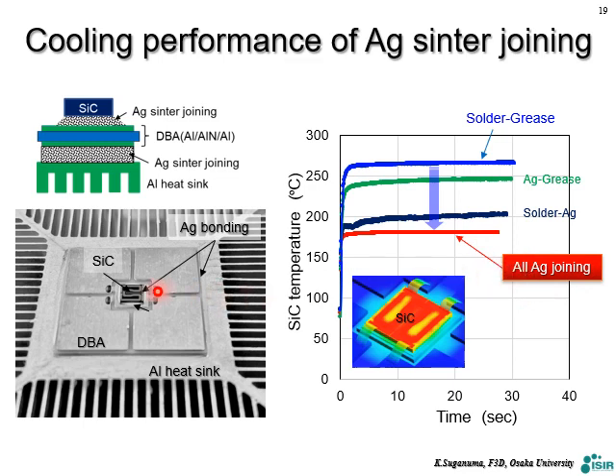So this is all silver sinter joint die attach, and also the bottom face is bonded by silver materials, because our silver materials can bond pure aluminum. And in this case, as you see, the temperature increases immediately, and after 2 seconds, it reaches just below 180 degrees C. This is the maximum temperature. So with the same power, we can keep the silicon carbide very cool, 100 lower than the conventional assembly structure. So this is our latest result showing great performance of silver sinter materials.